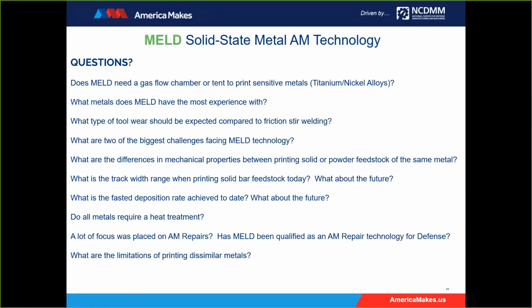We've done this, but we can't provide that data. It belongs to the domain of the company under NDA. But for the guys that want to try it out for the first time, we can do a series of tracks with different combinations of the 2 parameters we vary, which is torque and linear force. And then we can take it from there as deposited, and we can develop and optimize a heat treat for aluminum. Our heat treat doesn't respond to the industry standard. It requires its own unique recipe.